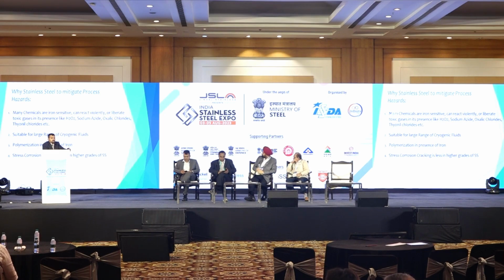Then grades of stainless steel are very good for stress corrosion cracking. There are higher grades like 904L, which has a higher percentage of nickel, which are good to be used where stress corrosion cracking occurs. Probably the 300 series is not that good, but if I go for duplex, super duplex, higher grades of SS, they are good for stress corrosion cracking.